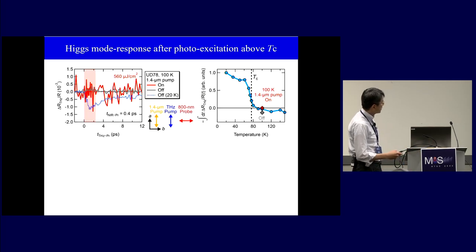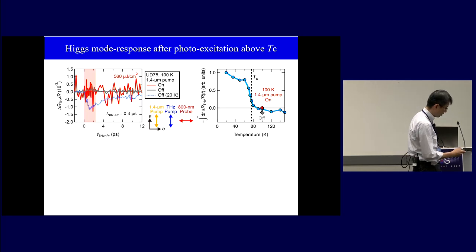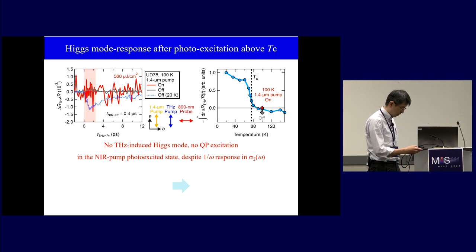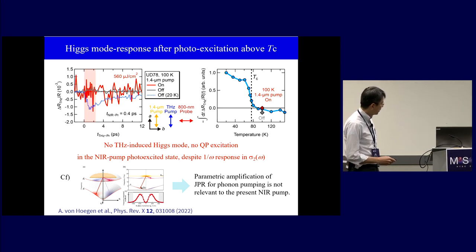And then this is the above TC result. So this is without pump, and this is after the pump. And even above TC, we don't see any signal appearing after the optical pump. So this means that there's no Higgs mode or no quasi-particle excitation in the photo-induced state. But I would like to say this might be different from the phonon pumping at 15 micron.